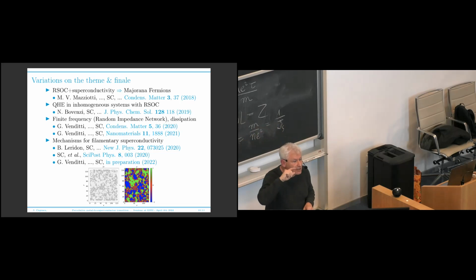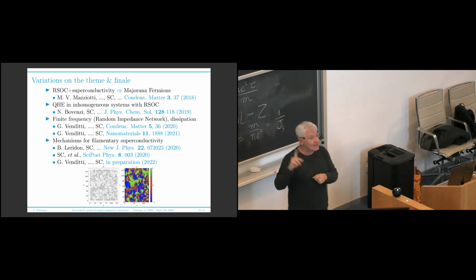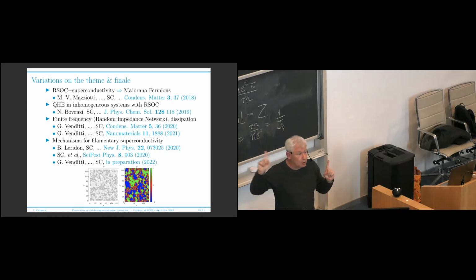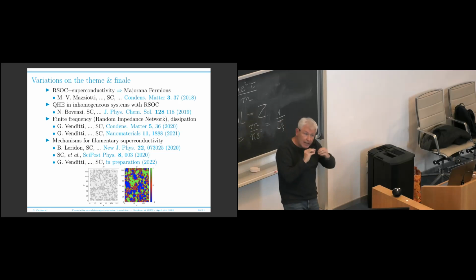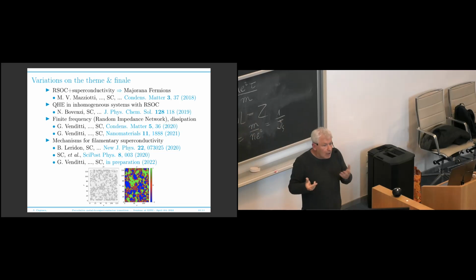It's reentrance of superconductivity due to disorder. This is very nice because it's something like Nicoletta was saying before the seminar began. There are situations where disorder is favorable to superconductivity. You are in a situation where, in the absence of disorder, you have only charge density waves or spin up and spin down. You put some disorder, and all of a sudden, superconductivity appears in your system as a filamentary, very weak, very fragile, but with a finite superfluid response.